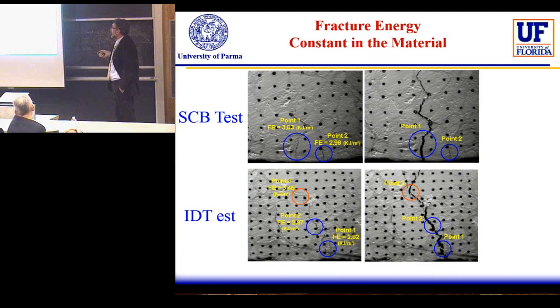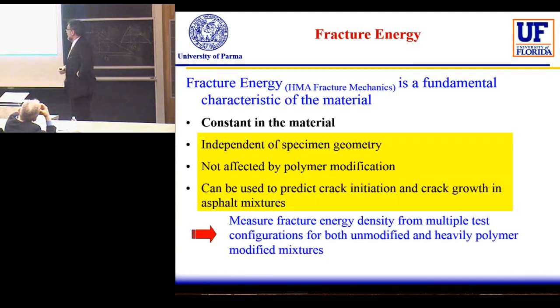And this was the very preliminary way to make the crack path. At that point, we manually made the dots in the material. The process started by identifying the crack, coming back, and calculating the fracture energy at different points in the material and in the different test configurations, and we found a very good agreement between the fracture energies calculated at the different points. So, using that result, we were able to show that it is a constant of the material, independent from the location of the crack and from the stress distribution behind the crack initiation.